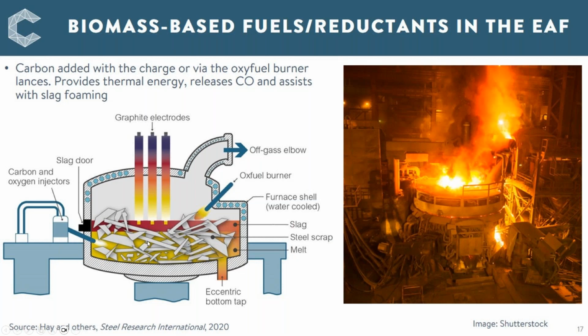And carbon actually provides a role in the electric arc furnace. So there is added carbon in the process. We have scrap material going into the electric arc furnace as well as direct reduced iron. This contains some carbon materials, some residues, oils, grease. There's carbon in the direct reduced iron as well. But sometimes carbon is also added in here. So coal and coke are added and other alternative fuels are added. And it provides a large fraction of the thermal energy needed to melt this iron down and start to remove carbon from it and form steel.